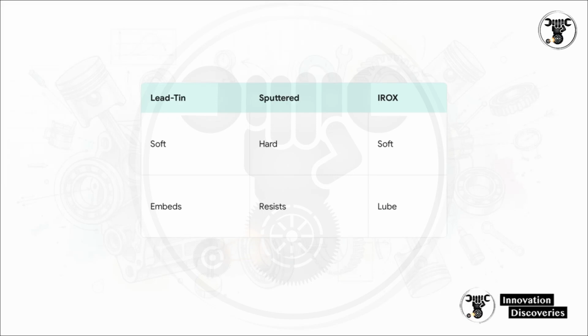Okay, let's step up to the workbench and actually compare the multi-layer composites we use to survive all this. First, you have your traditional lead tin overlays. These are super soft, around 12 to 18 Vickers hardness. That softness gives them incredible embeddability, meaning microscopic dirt and debris safely sink right into the soft metal rather than scoring your expensive crank. Then we have sputtered aluminum tin, or ALSN20. These are plasma deposited in a vacuum chamber, giving them a much higher hardness at 25 to 35 HV, which provides vastly superior fatigue resistance for high-performance builds.